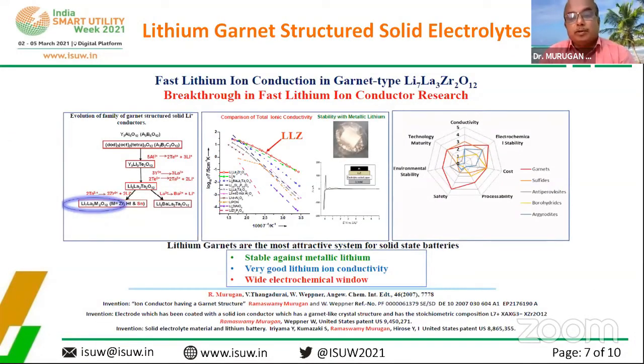But we are much more interested in oxides because, from the commercial point of view and the technology maturity level, oxides have a slightly better advantage over these. So this is our biggest breakthrough, the fast lithium-ion conductors, particularly the zirconium-containing lithium garnets. It is the ideal material because it possesses the highest lithium-ion conductivity and it's stable against metallic lithium. No other oxides will be stable against metallic lithium. The beauty of this combination is what makes it most stable against metallic lithium.